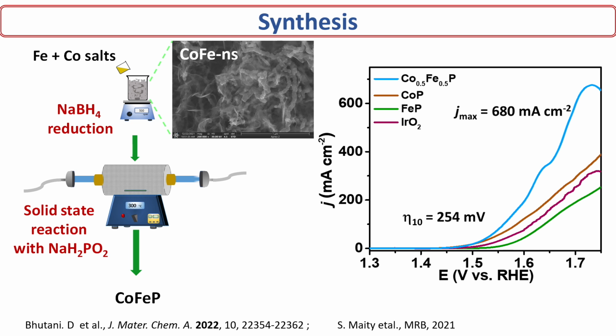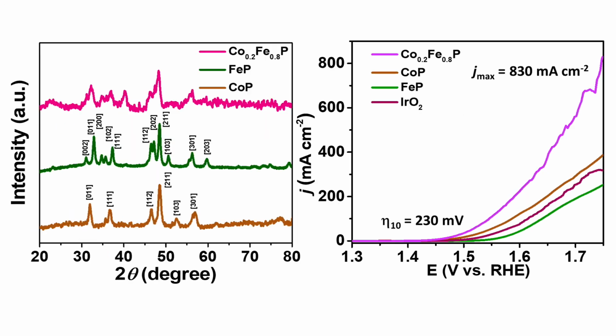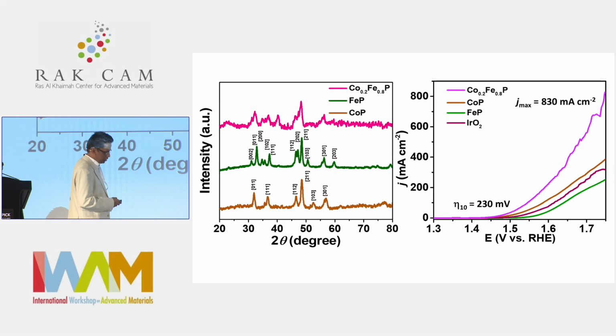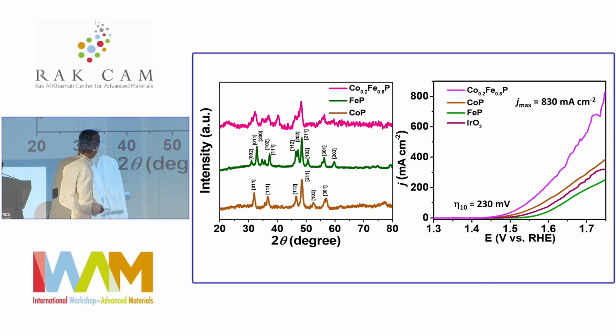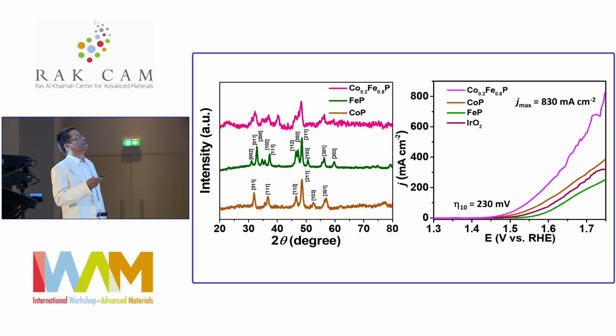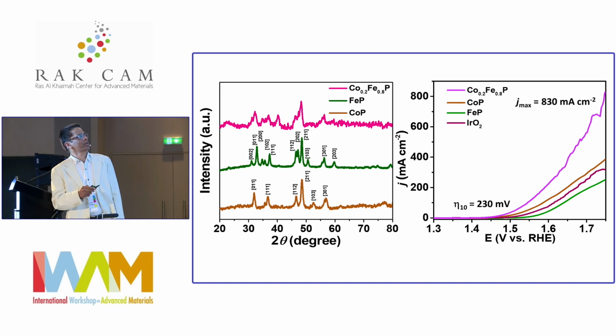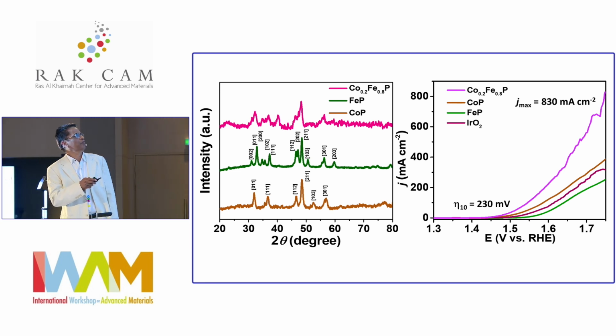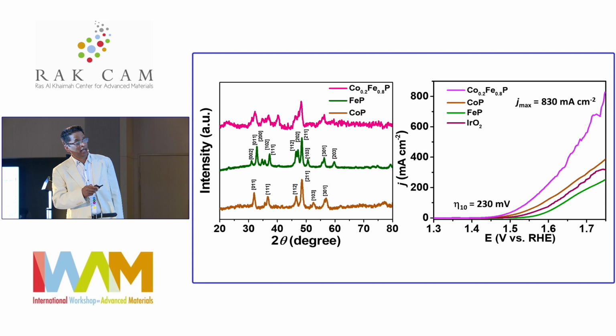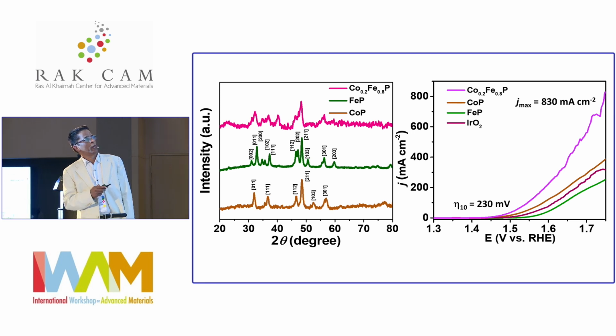And it shows very good activity, almost 680 milliampere per centimeter square at around 1.7 volts. So eta 10 is still a little high. Then we looked at the structure, but it is very difficult to identify what phase is forming. We are getting almost similar iron phosphide, cobalt phosphide structures, so it's not clear whether it is one phase or different ones.